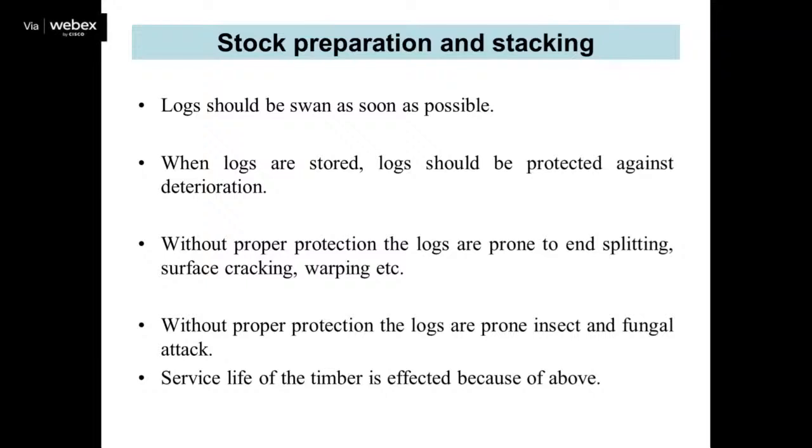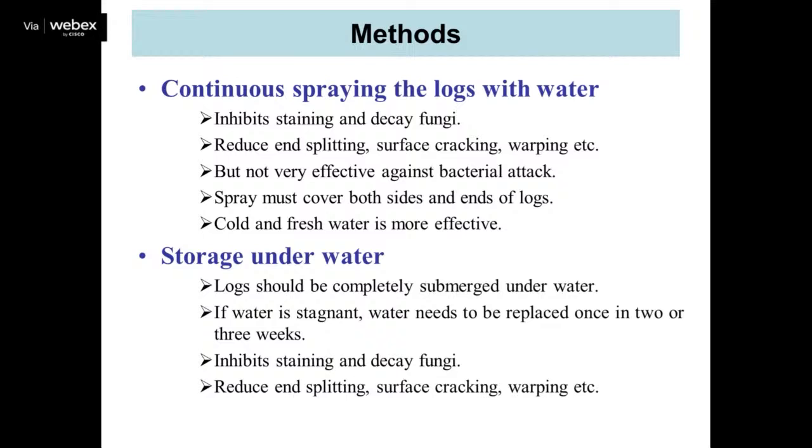Other methods are continuous spraying of water on the log, which inhibits the staining and fungal decay organisms, and also reduces splitting. It also prevents surface checking and warping. But it is not that effective against bacterial attack, because if the water is not continuously changed, bacterial attack may happen and cause some damage to the wood. Cold and fresh water is more effective.